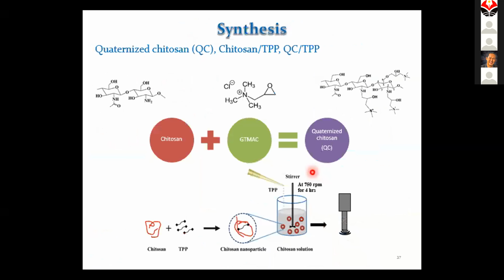That's why we developed a material that comes from chitosan. This is the structure of chitosan. Actually, native chitosan can have positive charge in the structure through protonation of the NH2 group. If we dissolve chitosan in acidic conditions, it has positive charge. However, this is not quite effective, so we want to introduce permanent positive charge into the structure.